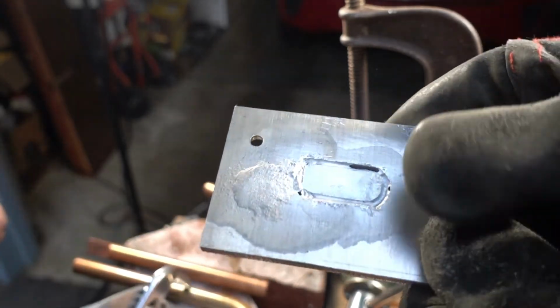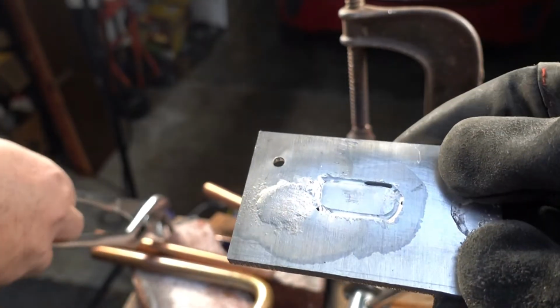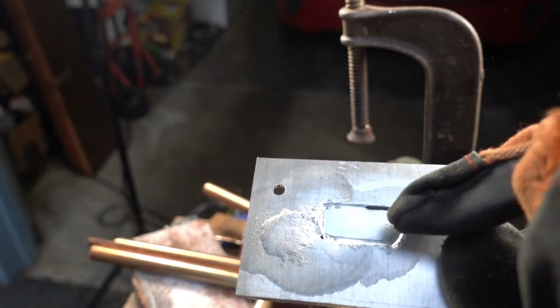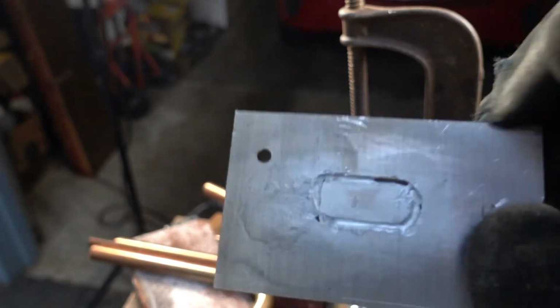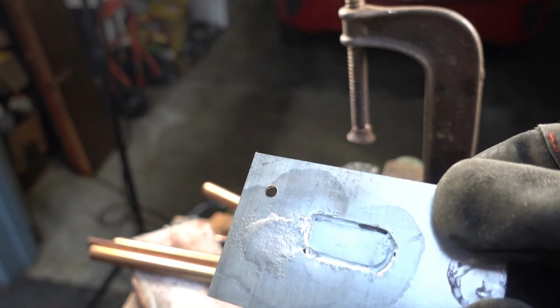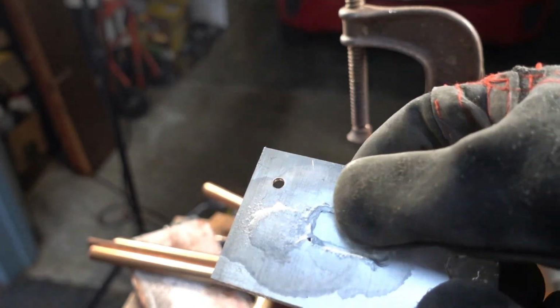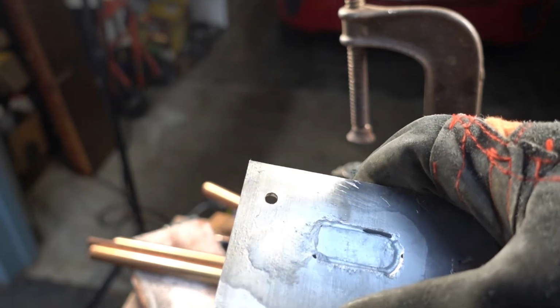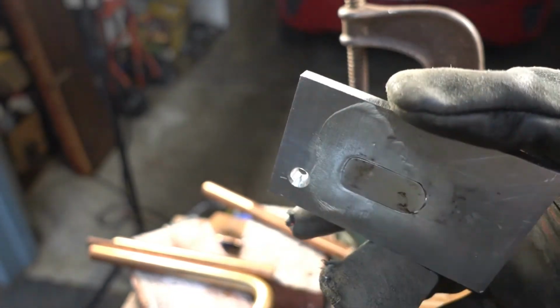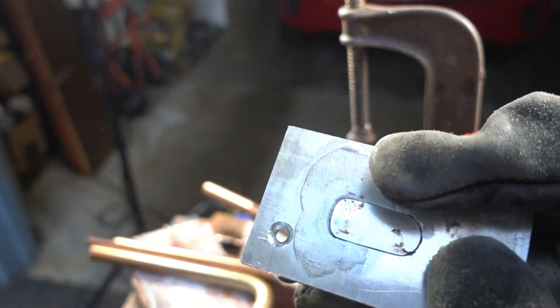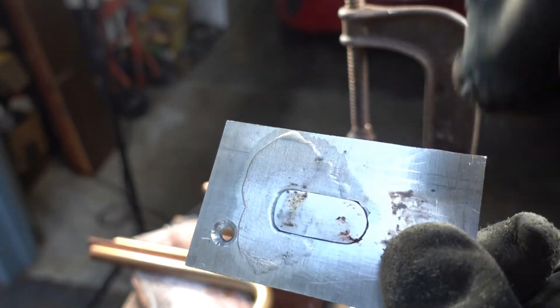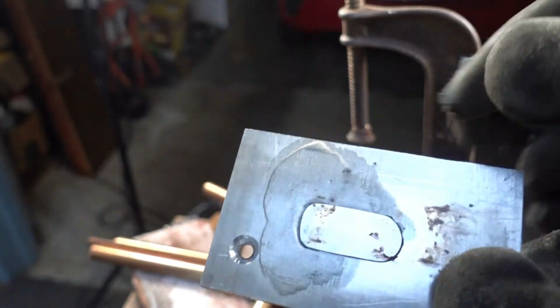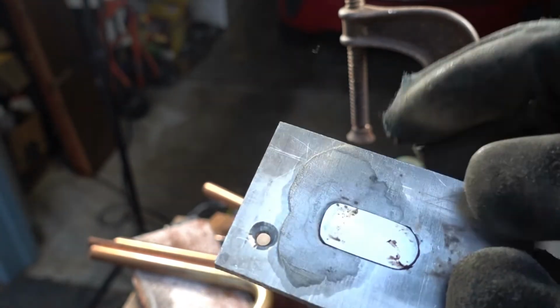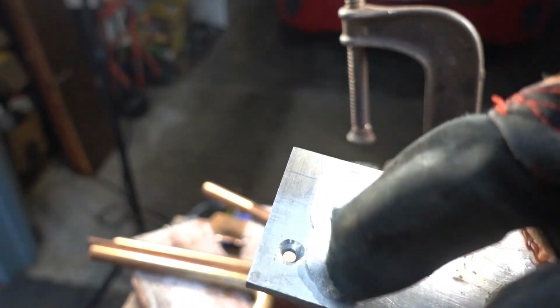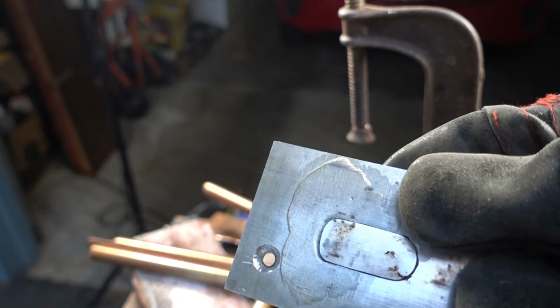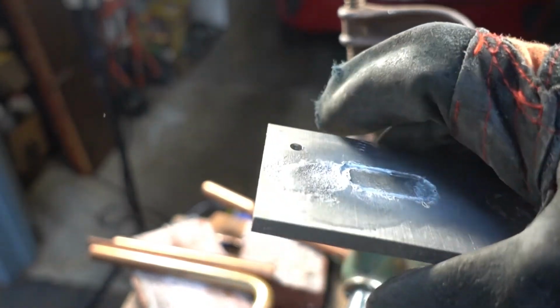Okay, it's still hot, but it's cooled down some. You can see what it looks like. We have a void right here. The filler aluminum shrunk. The aluminum weld did shrink in the groove. Let's look at the back side. We were expecting to see some aluminum filler migrate around the sides to the bottom, but that really didn't happen. We do have some filler down here, and that probably came out when I did that first part.